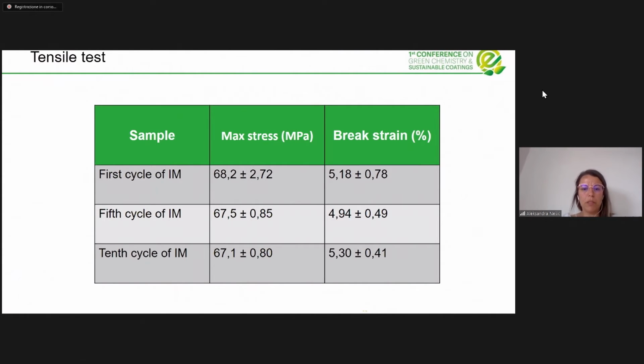When we tested the mechanical properties, we also have the tests for all 10 cycles, but the results are very similar. So we took just the first, fifth, and 10th cycle of injection molded samples. As you can see, the maximum stress and the break strain in percent are in the same range. Maybe the difference is 10%, and there is no significant difference between the mechanical properties of first cycle samples and 10th cycle samples.